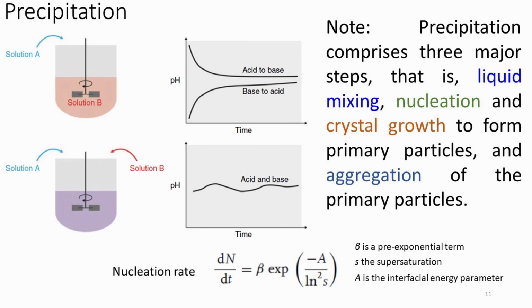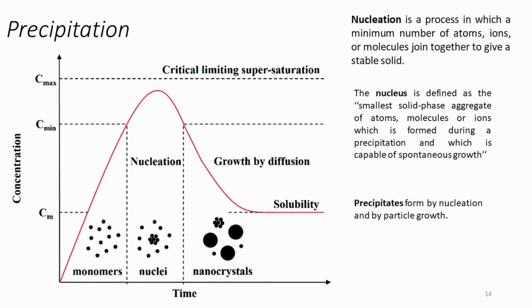Precipitation includes three major steps: liquid mixing, nucleation and crystal growth to form primary particles, and aggregation of the primary particles. The process mostly starts with the formation of clusters, which are capable of spontaneous growth by the subsequent addition of monomers until a critical size is reached. Clusters smaller than this size tend to redissolve in solution, while larger clusters will continue to grow.